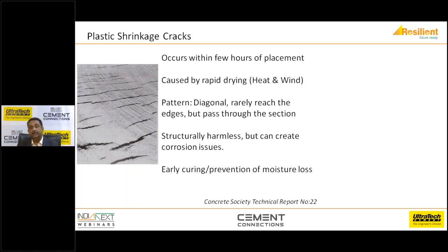Why does this happen? This happens because of the loss of moisture in the early age of the concrete. When I say early age, when the concrete has started setting, but the concrete is not hard enough to take the load. So when you lose moisture from the surface, capillary tension is created on the surface of the concrete, and the concrete per se is not strong enough to withstand it, and then it cracks.